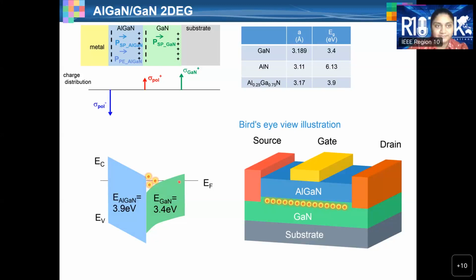Okay. The two-dimensional electron gas is actually due to the internal polarization fields, which force the electrons to move from left to right. And when you ask me what is the physical source of this 2DEG, this is actually a debate regarding the source of the 2DEG. In my personal opinion, the source of the 2DEG is due to the surface donors. There's a defect level here in AlGaN, and the surface donor acts as the source of electrons to the 2DEG. That's my personal opinion here. I mean, there is a donor here on the AlGaN surface. And this is a defect, and probably this is due to nitrogen vacancy.